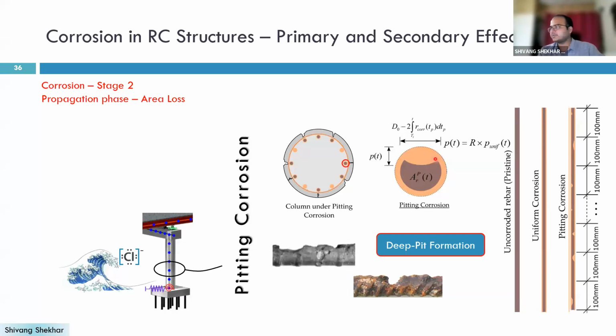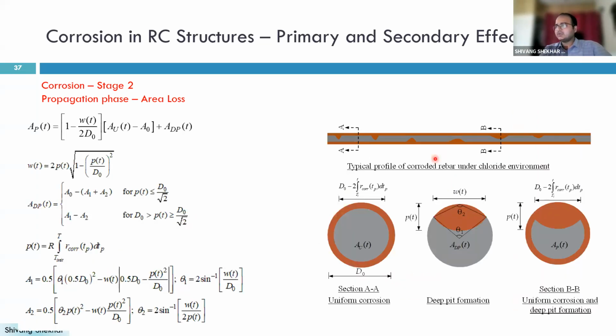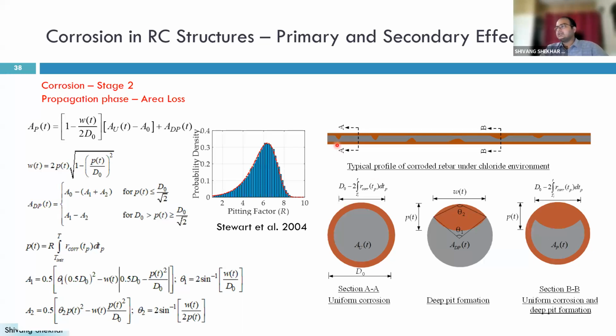The work done by Val and Stewart involved experimental tests in a chloride environment, and they tried to model this. There are some equations given for how to get this area loss at a cross section. Here A is the uniform cross section, and if we take the area loss at section BB, you can see the uniform area loss, and in addition to that there is a pit. Some formulations are available in the literature which can be used to calculate this area loss. Again, for representation purposes, I have also shown here that the pit depth is very small, and here it is a little larger.